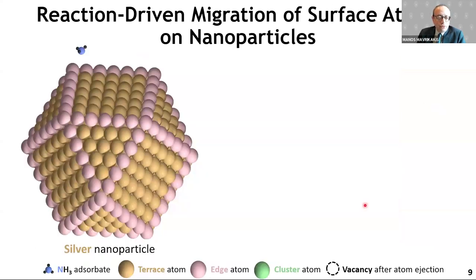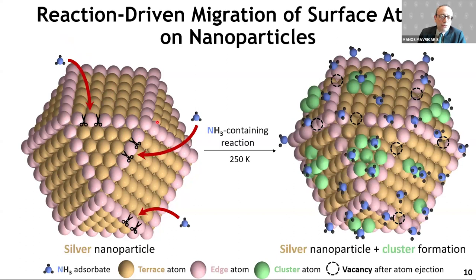And because they say that a picture is worth a thousand words, what I would like to do now is to show you the standard cuboctahedron, which is what most catalysis practitioners will have in mind for transition metal catalysis. This is a silver used for ammonia oxidation for all practical purposes. Here you see one facet with tetragonal symmetry. Here is another facet of the nanoparticle with hexagonal symmetry. These are step edges. Here you have a corner site, etc. And here I have an ammonia molecule coming down from the gas phase. And then you see a pair of scissors for breaking silver-silver bonds and generating an adatom with ammonia on top of it. Imagine now that you do this with much richer environment, higher numbers of ammonia molecules. And here is the new picture that develops for steady-state catalysis.